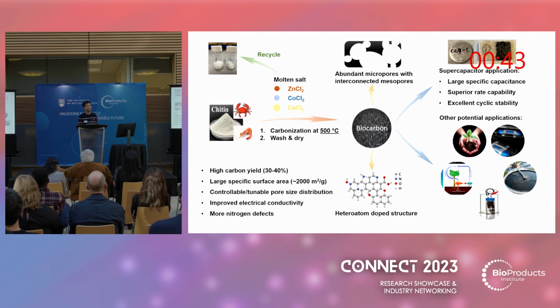Our innovation centers around an adaptable and recyclable molten salt system for carbonization of chitin from crustacean waste at a mere 500 degrees C. Upon melting, the salt ions undergo fast diffusion towards active sites, creating and retaining numerous pores whose sizes are modeled by the salt cations. So the yielded biocarbon shows ultra-high surface area, tunable pore size, and various heteroatoms, yielding outstanding supercapacitor performance.